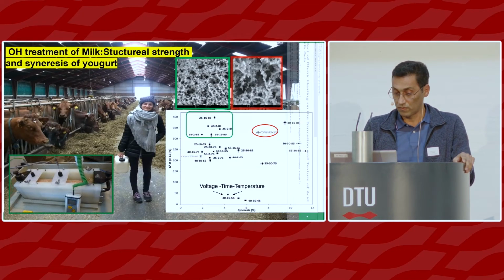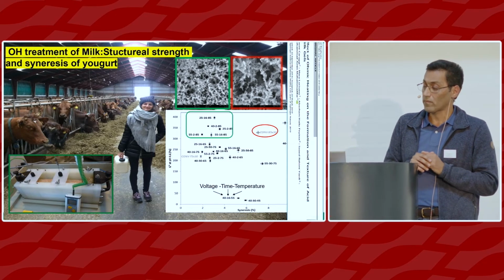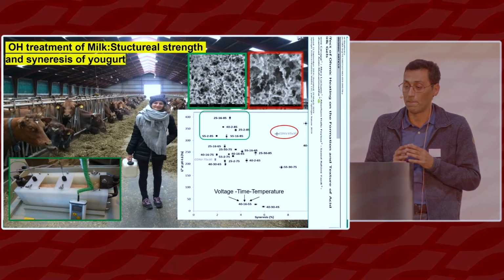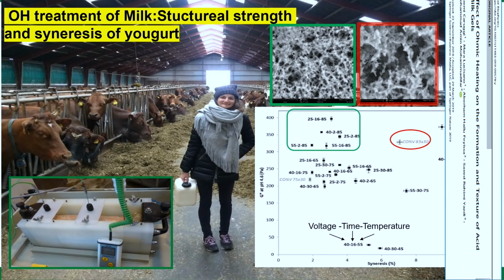And then we just moved ahead, and we used ohmic heating to treat milk that is going to be used for making acidified gels like yogurt. And then, as you can see here in this graph, in the green box, we have some ohmic heat treated samples that have higher structural strength and lower syneresis. Usually, you can reach this only by adding dry matter, like 7% dry matter to milk, so that you have a strong gel.